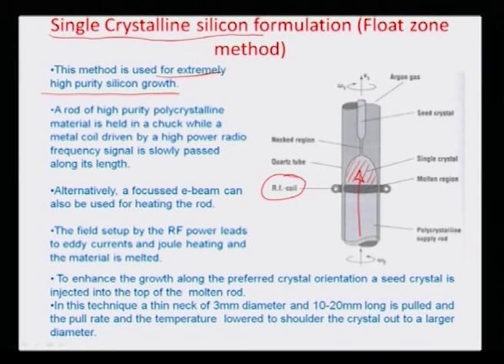Okay, and on the other side you lower the seed crystal into this orifice here, and the seed crystal is actually used as a template for growth of this polycrystalline material being pushed through the orifice onto the other side. So from the necked region, really in this particular region, the seed crystal grows and makes a single crystalline silicon of the type of seed crystal from the polycrystalline melt which you are pushing through this particular